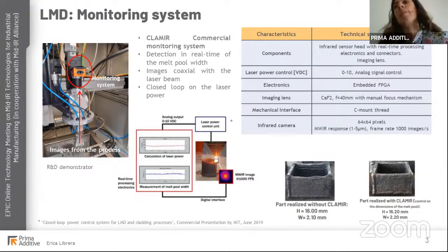The system is always able to collect the information, but also to act directly on the process because it works in closed loop control on the laser power. This kind of system is particularly indicated for very long processes in which we have the remelting many times of the deposited layer. At the same time, it's very useful in the case of critical features like corners, sharp edges, or curvatures that generate instability in the process.